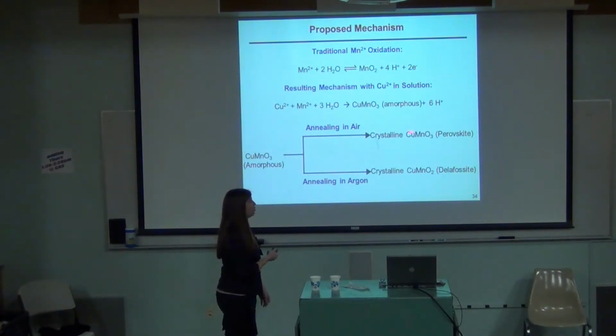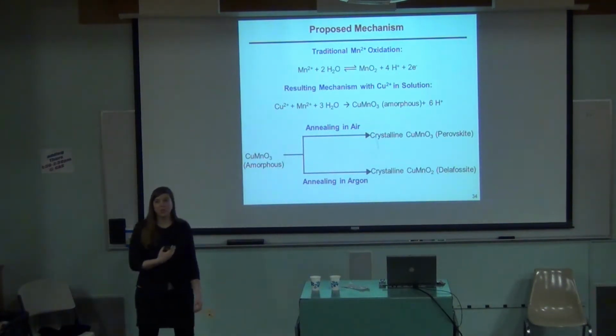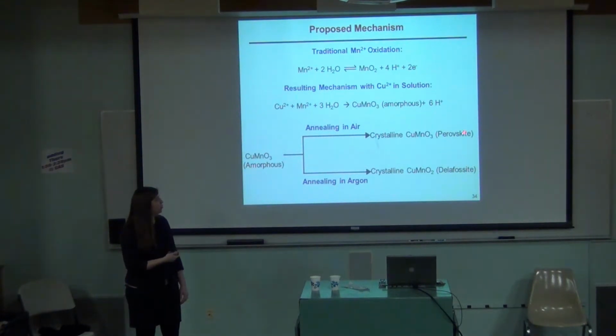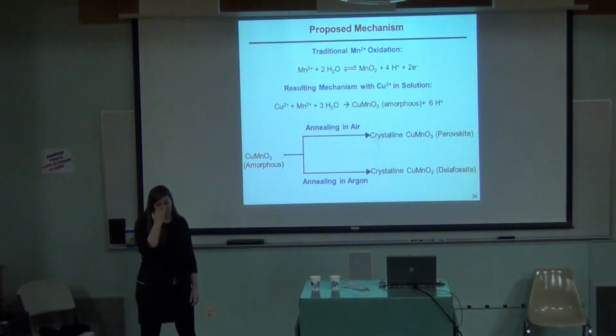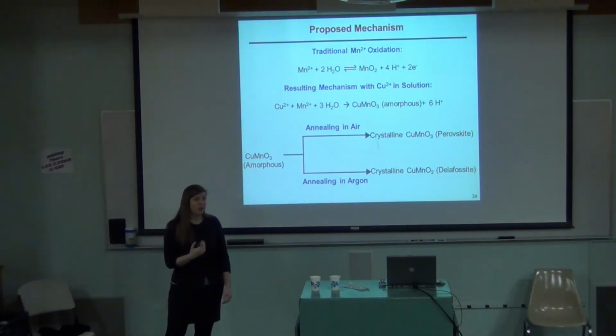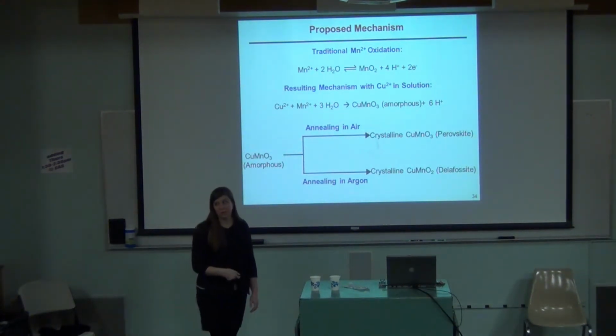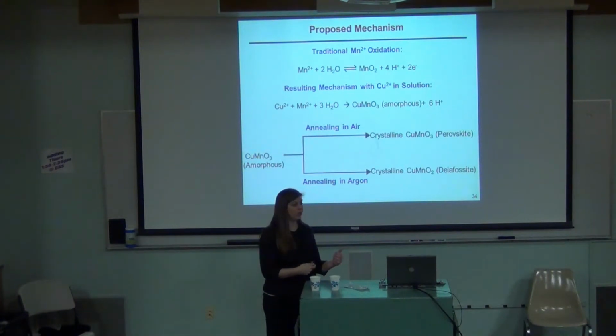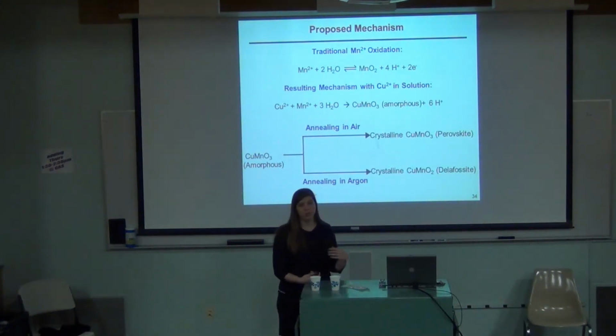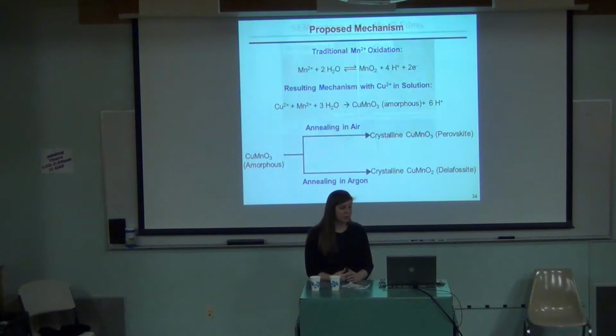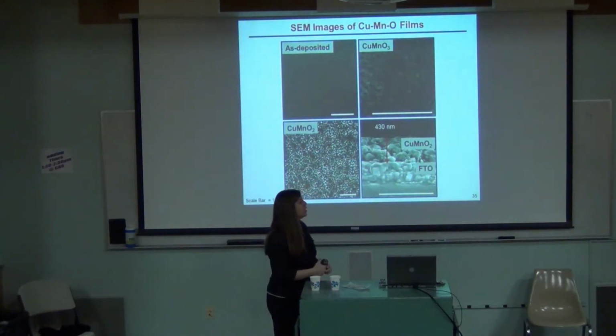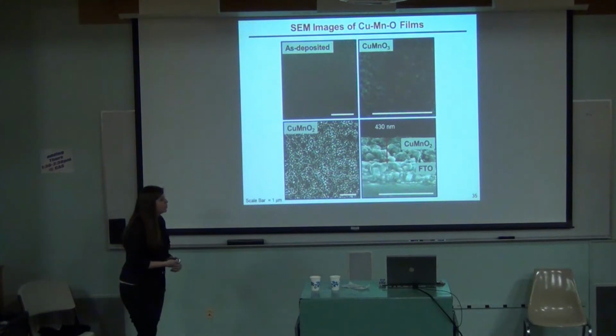So that structure is actually perovskite. So when you annealed these, which I'll show you a picture of, that actually forms perovskite because it's formed that way amorphously. But something magically happened when we annealed in argon. So without extra oxygen in the tube furnace, we were able to reduce the copper and keep the manganese in the 3+. And then that also took away one of our oxygens because it was so oxygen deprived when you're flowing argon through your tube at really high temperatures. So that was encouraging because we could prove that they were crystalline, and I'll show you XRD of that.